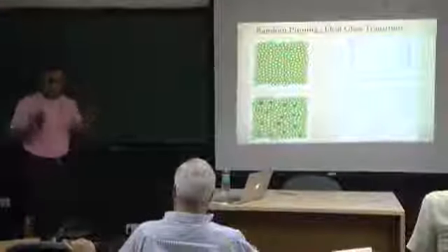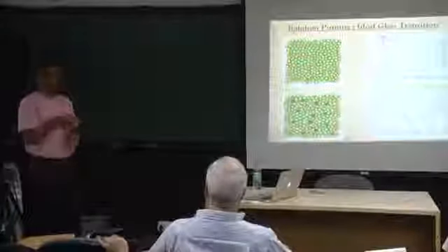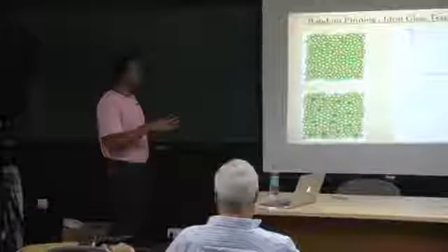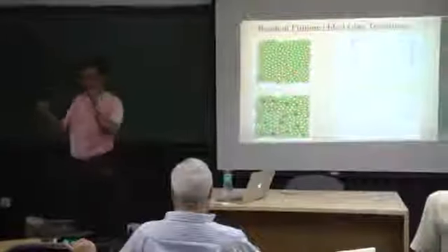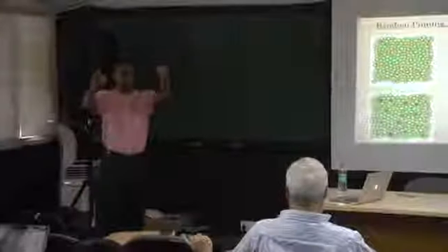This is very important here. I do not have to do re-equilibration. I just start from an unpinned liquid and freeze some particles, and then the time scale of that pinned system will be larger than that of the unpinned system. And the point is, if I increase the pinned fraction to a certain critical fraction, will I completely freeze the dynamics?